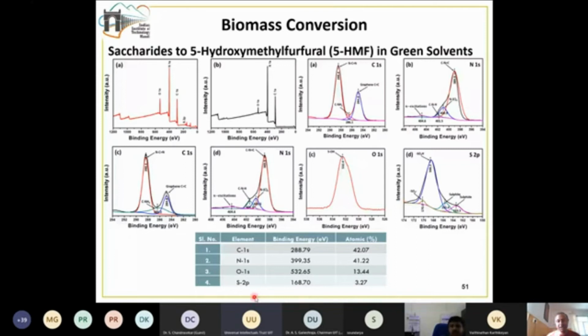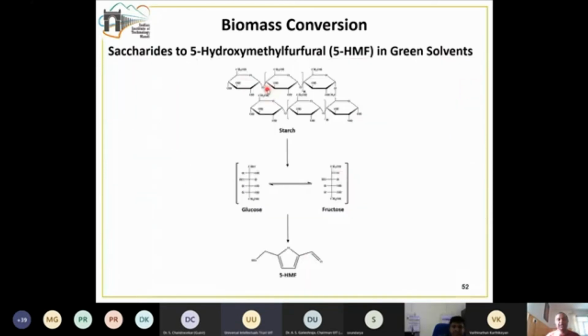And we deciphered that about 3.27 atomic percentage of sulfur is present in our sample. Then we used this material as a catalyst for this conversion reaction. So starch gets converted to glucose and fructose, which eventually gets converted to 5-HMF.